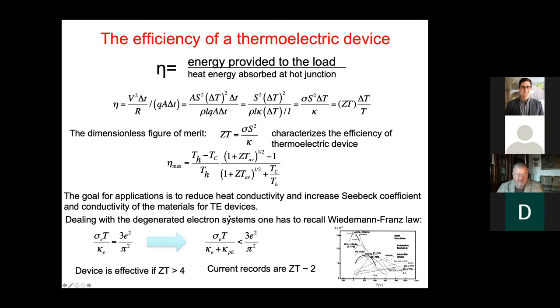the figure of merit. But the obstacle for metals is the so-called Wiedemann-Franz law. Because for metals or for doped semiconductors, we know that conductivity multiplied by temperature divided by heat conductivity due to electrons is 3e² divided by π². So if I include phonons, they do not help to conduct, but they will increase my denominator. So this factor will be even less than 3e² over π². This is an obstacle. So how to decrease heat conductivity, not touching electric conductivity?